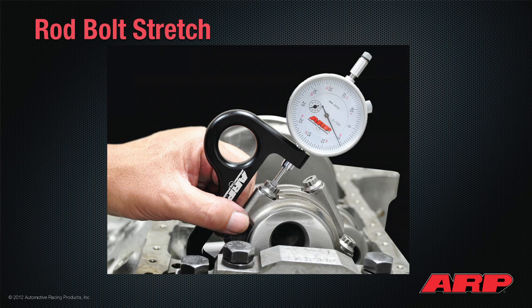In a connecting rod, one of the quickest and easiest ways to record that stretch is using a stretch gauge, either ours or somebody else's, it doesn't really matter. The most significant thing is that you've got a dial indicator here. A standard dial indicator has a very weak spring because it's just designed to measure difference. In this instance, we need a lot of spring pressure because we've got to get the points to register in the 45-degree or 90-degree included angle at the bottom of the lightning hole, and we also put a 90-degree center drill dimple in the other end.